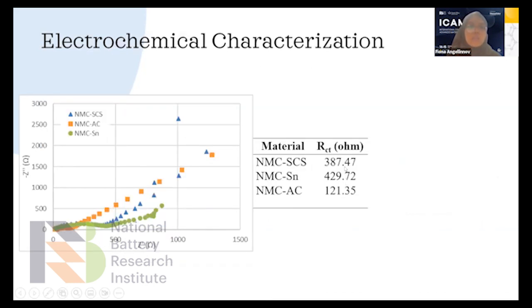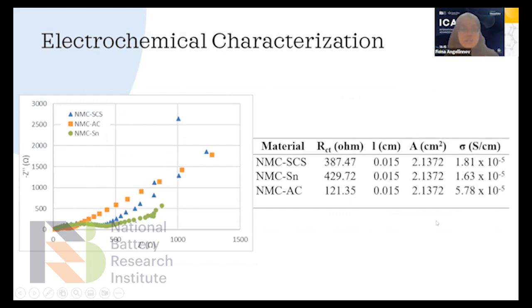And here is the electrochemical characterization using electrochemical impedance spectroscopy. We can see that the R_ct for NMC-AC is the lowest, and therefore the conductivity is the highest.